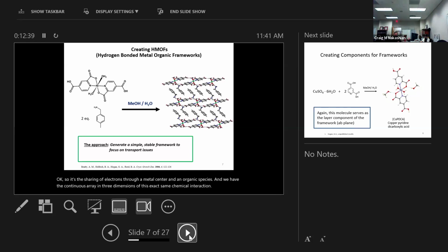The difference where I come in is we use hydrogen bonding to associate and connect our framework together. So we have here a basic metal dicarboxylic acid. In this case, it is nickel-based. So we're looking at the molecule on the top left-hand side. It has 2 carboxylic acid groups on the peripheral edges of our molecule, and we're going to interact it with what's called an amine, 2 equivalents. So we're going to give 1 amine for each carboxylic acid. So 1 NH2 is going to interact with this OH species.